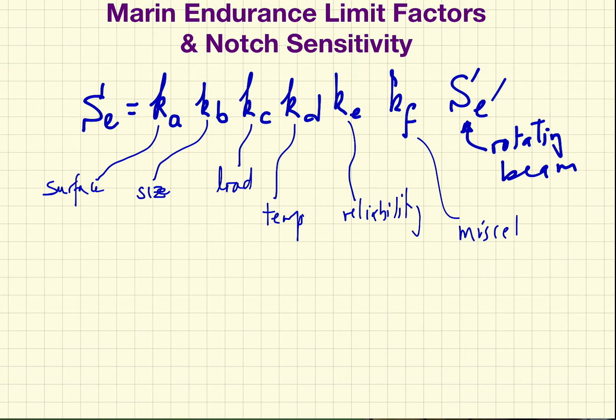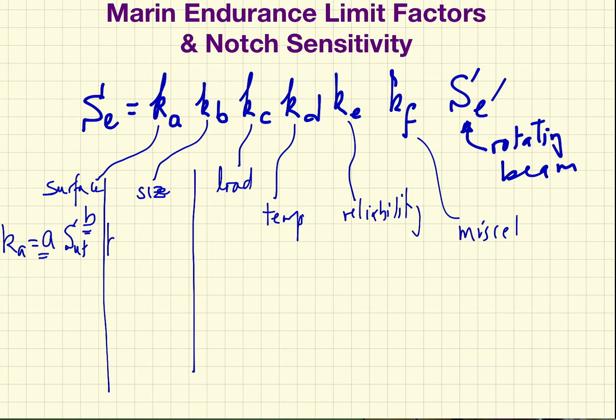So the way that these empirical factors are done is that if we look at the surface factor, ka, it is expressed as a constant times the ultimate strength raised to another constant. And the values of A and B will be obtained from tables, as I'll show you in a minute, depending on the surface finish. The size factor is also obtained, kb, as the diameter divided by 0.3, this is in inches, to the minus 0.107, and that is for diameters that are in the range of 0.1 inch to 2 inches. And then it has a different form for larger diameters, as I'll show you.